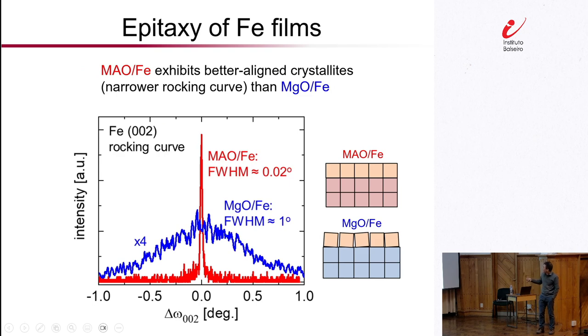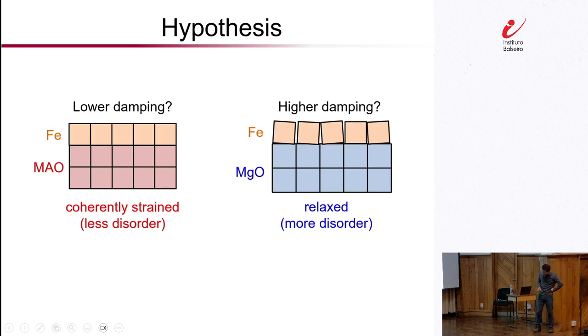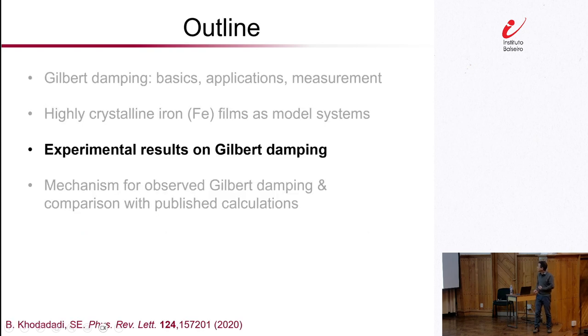We can also take a look at our XRD rocking curve measurement. So without going into a whole lot of gory detail here, we again see a much taller and sharper peak for iron on MAO. What this indicates is that the different crystallites within the film are much, much better oriented along the same direction with iron on MAO. Okay. Great. So right here we have two kinds of epitaxial films. Again, I emphasize that they are both crystalline, but one of them has a much, much better crystalline quality than the other. So at this point, you might simply hypothesize that with this better crystalline quality in iron on MAO, we expect to see lower damping. But of course, the question is, is it actually true? Okay. So that's what I'm going to show you next.